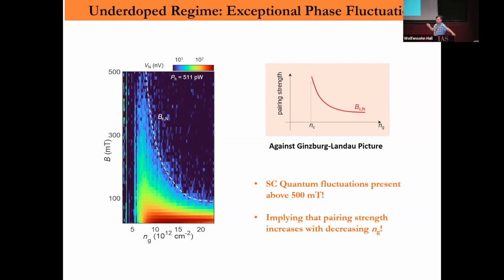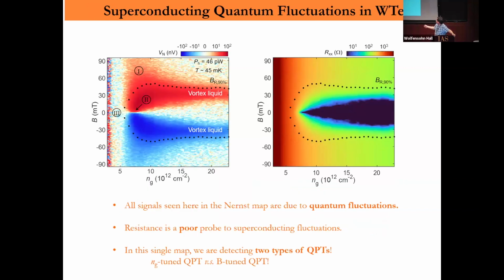So first of all, that's very clear already. Where we see here, it starts to disappear—there is very weak signal. So here it's not really getting into the insulating regime. It's still kind of metallic, but it is insulating, though not really at charge neutrality, where you don't see the Nernst signal—you see a lot of noise. It's not Nernst signal because it does not change sign.